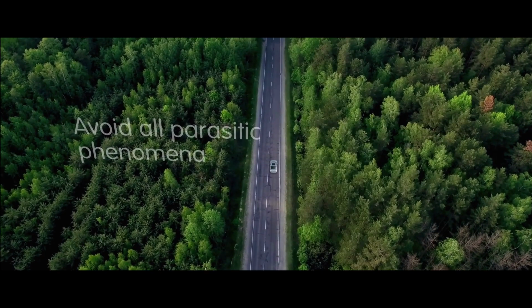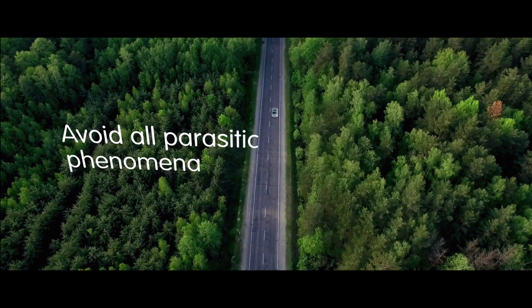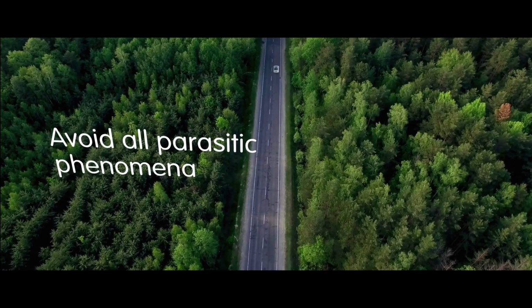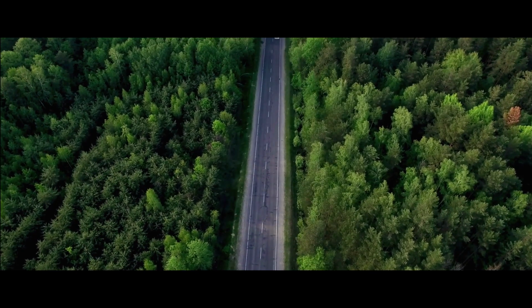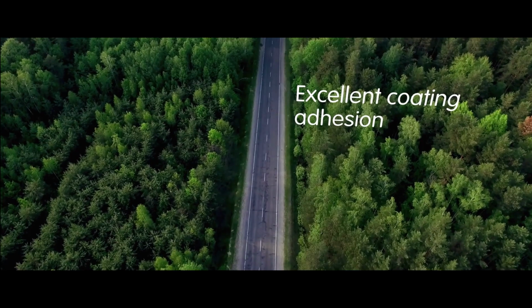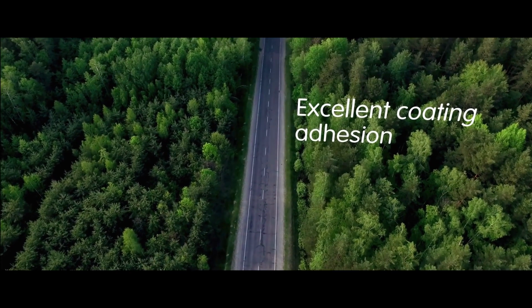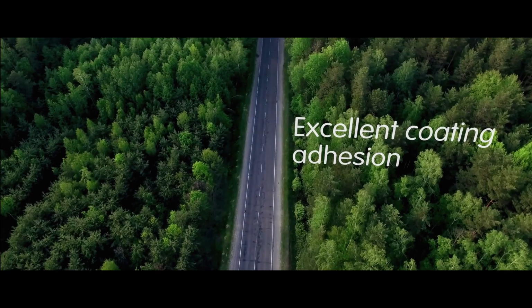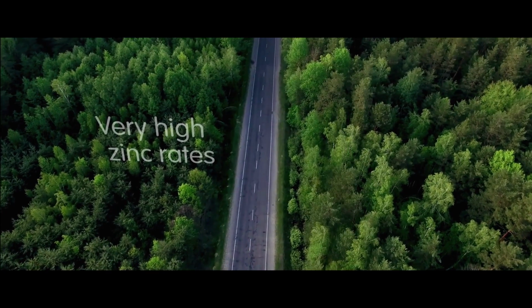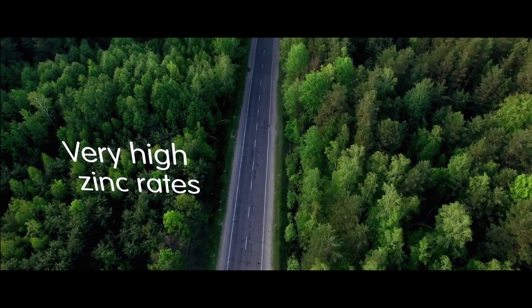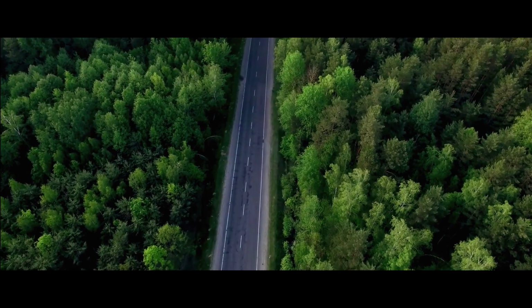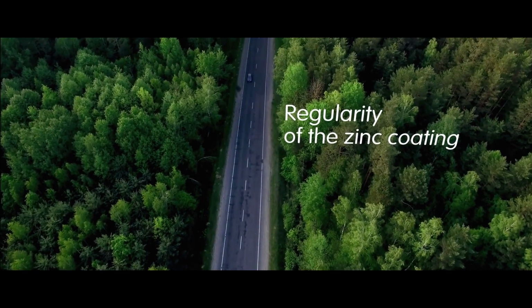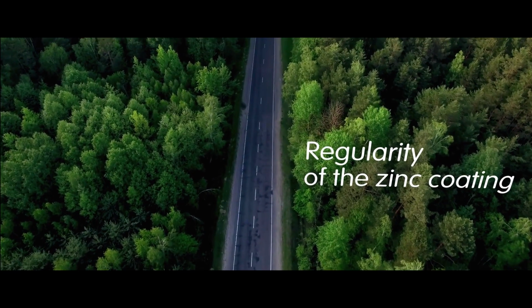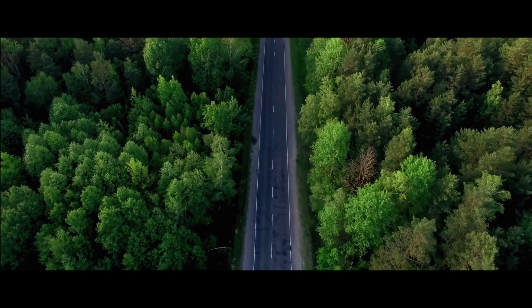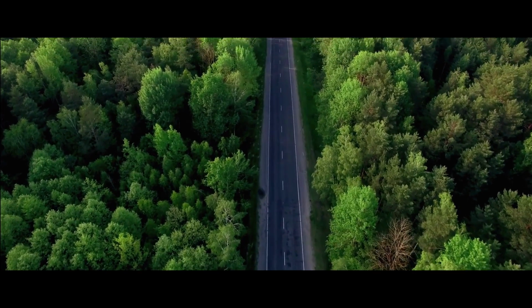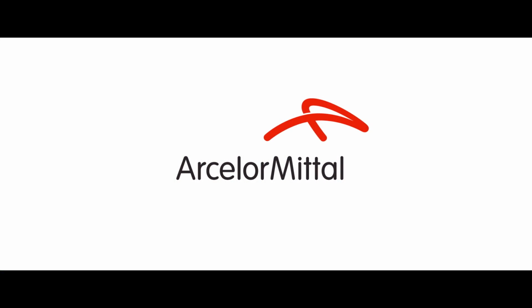Working in a vacuum avoids all parasitic phenomena, causing both the zinc and steel to oxidize, and it enables lower evaporation temperatures. It ensures an excellent adhesion of the coating, no matter the steel grade, and avoids ultra-high-strength steel becoming more brittle under the influence of hydrogen. It leads to very high zinc rates, generating almost no losses or rejections of the material. It ensures an excellent regularity of the zinc coating. By continuing to stretch the boundaries of its technologies, ArcelorMittal is able to produce the steel of the future.